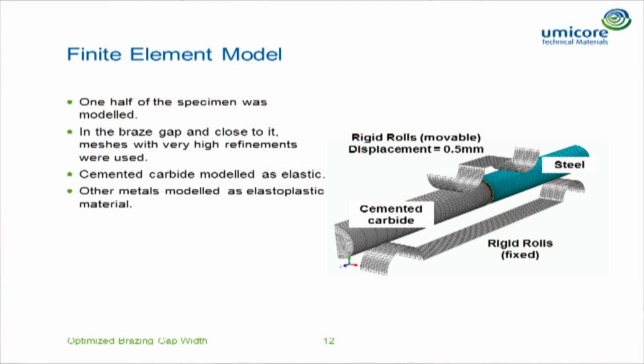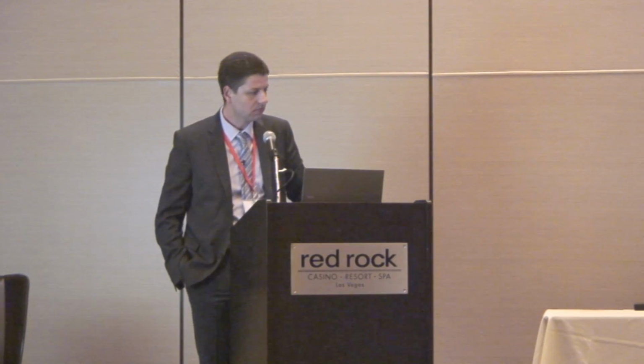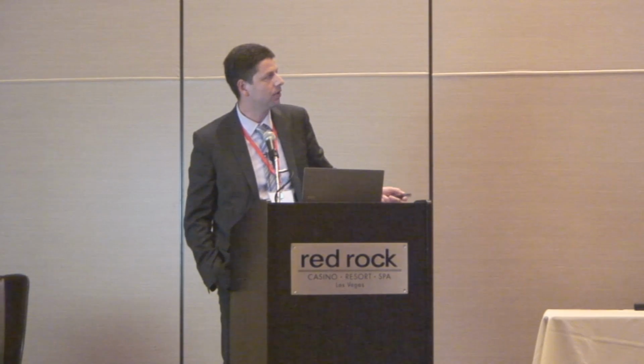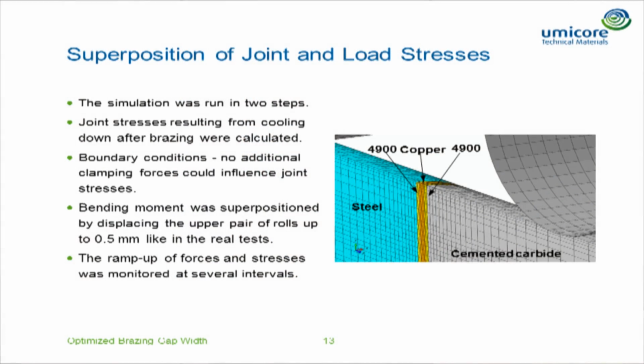So, besides the practical things, we also made finite element analysis and built up a model. But we made only a half model, and afterwards we doubled it for the calculations. When we get closer to the joint area, the net was set much finer than at the ends. And here you can see the net for the sandwich brazing alloy, where you have the two brazing alloy layers and the copper in between.